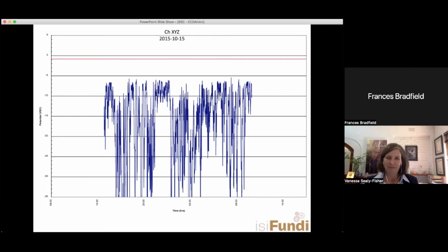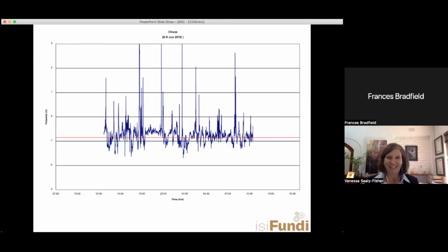While this isn't good, as you can see, it's not stable at all. We are going negative, which means we're not forcing millions of electrons out of our pipeline, which again means that we're not actively corroding the pipe. I will mention, however, that I'm sure we've all heard of overprotection. We're not keen on having huge overvoltages on pipelines. We can get hydrogen embrittlement, for example, or disbond our coatings. So it's not a great thing, but it is better, at least, than having a whole lot of current coming out. And I presume you have another example where we're very worried about the pipe.